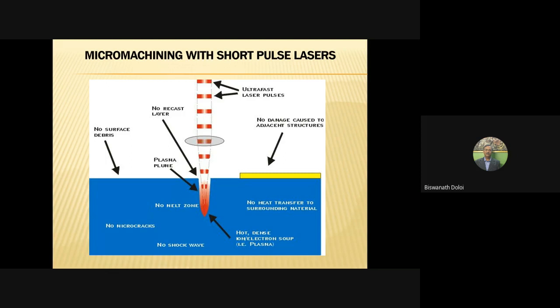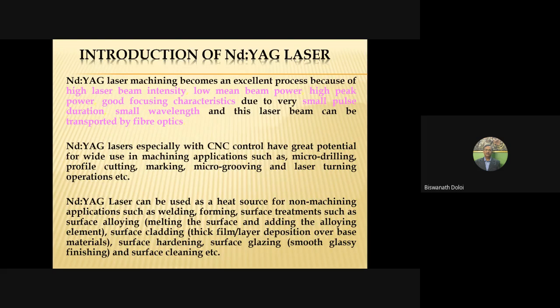So gigawatt range power for a very short duration, nanosecond, picosecond or femtosecond, then there is no time to melt, directly the solid is vaporized. So no melting means no melt zone, no micro crack, no thermal damage. All the problems are eliminated when you are using a short pulse. So selection of laser is very important when you are going for machining, especially micro machining applications.